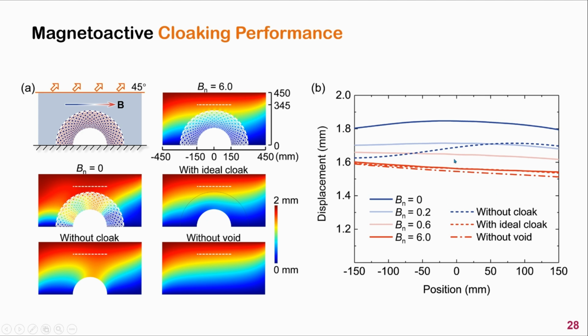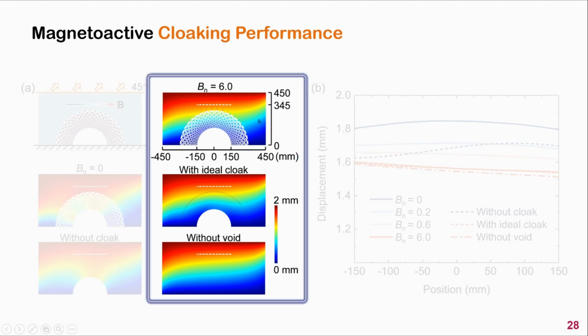As can be seen here, as the external magnetic field increases, the response of the system with the lattice cloak approaches that of the system with the ideal cloak. In particular, when the intensity of magnetic field is large enough, the performance of the lattice cloak matches well with the performance of the ideal cloak. Both of them effectively make the void invisible from the background.